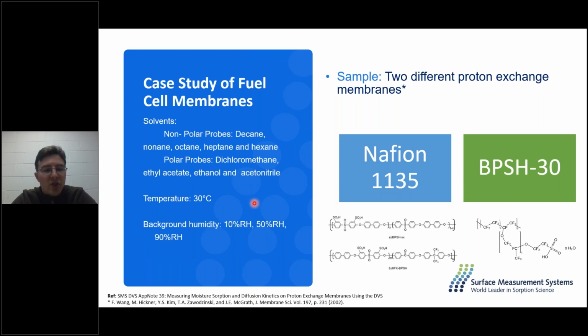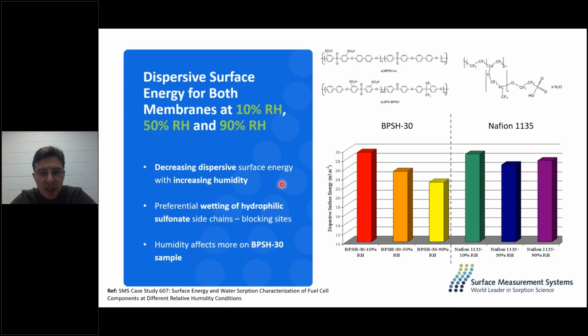And then what we wanted to do was see how humidity would influence the energies that we measure. And here we can see the results of these studies. So here we're looking at the dispersive surface energy, how these materials react. So for our membrane BPSH30, we can see that the more humidity we're introducing to these membranes, the lower the dispersive surface energy is. So we can really see that the activity of these membranes can be highly affected by the humidity that we are introducing.